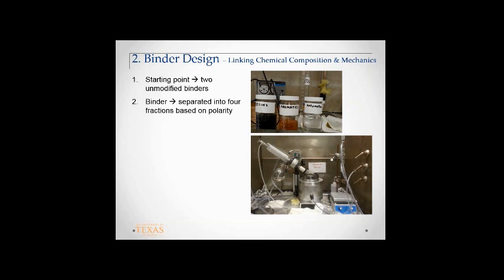and you start breaking it down. So you've got saturates, then aromatics, where the color gets a little bit darker. These are a little bit more polar than the saturates. Resins are even more polar, and get even darker. And then you have saturates, aromatics, resins, and asphaltenes. I don't have asphaltenes in this picture because asphaltene is a dark black powder. It's literally a powder. Inadvertently it got chopped off, but at room temperature, it's not a liquid.